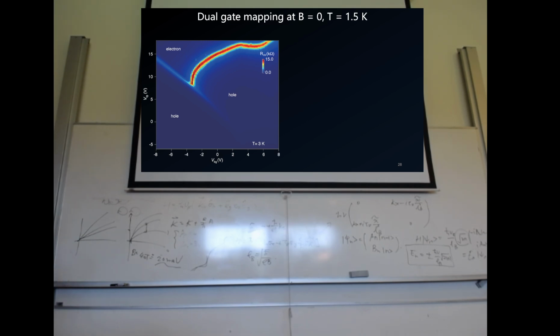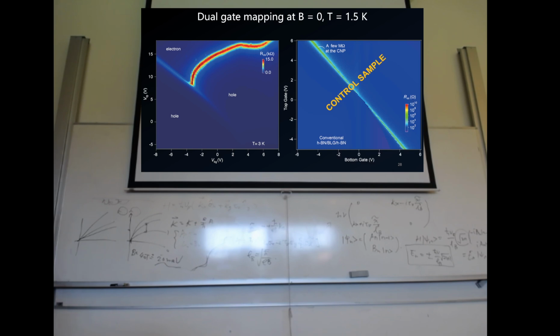There is a more resistive peak showing up, and it's bending back. So we mark all these regions as hole and electron. That means this is the new charge neutrality point defined. We know that because we measured the Hall effect under a finite magnetic field. This is a control sample of conventional graphene. It should look like that. This is the charge neutrality point, where the carrier density is supposed to be 0.